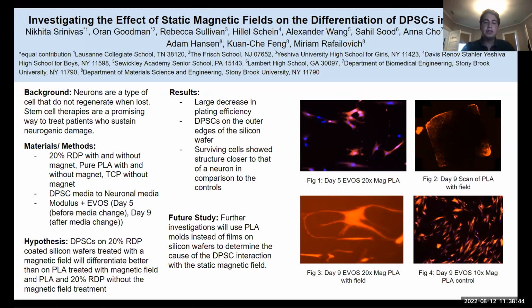And then what was interesting about the RDP samples in the magnetic field was that the films that we were growing the cells on started falling off, which in turn made the cells die. But we might attribute this to the ions in the RDP clay being moved around too much by the magnetic fields, because ions are moved in magnetic fields, thus weakening the film and making it fall off.